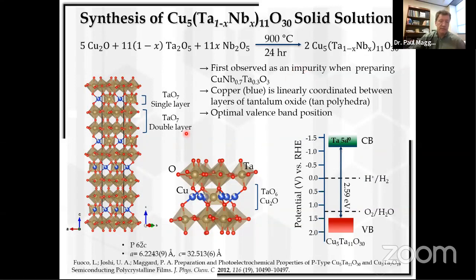Okay, so we chose this 51130 phase, and its crystalline structure I described earlier, pentagonal bipyramidal layers with copper between those layers. And here are its valence band and its conduction band positions. Okay. We chose it because the valence band position is appropriate to drive water oxidation. We want to lower the conduction band now down to here. We knew we could do that with niobium.